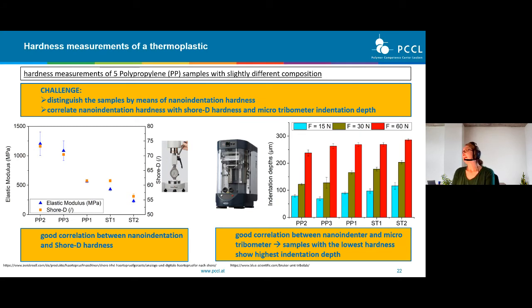And on the right side, you can see microtribometer indentation. These are the same samples as on the left side. We have a good correlation between nanoindenter and microtribometer, because the samples with the lowest hardness show the highest indentation depth, which is here this ST2 sample, which has the lowest hardness, and on the right side, the highest indentation depth. So this also correlates very well.